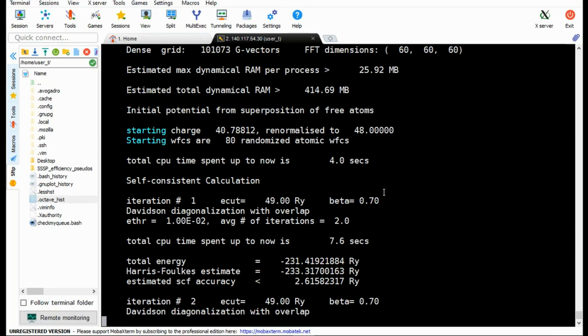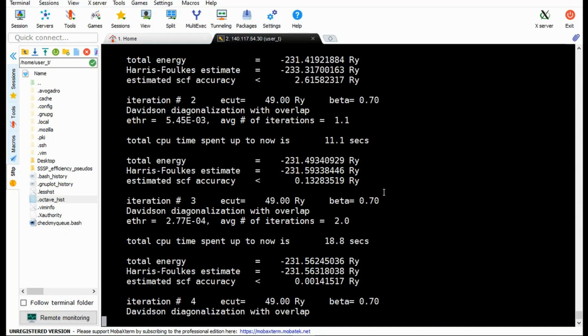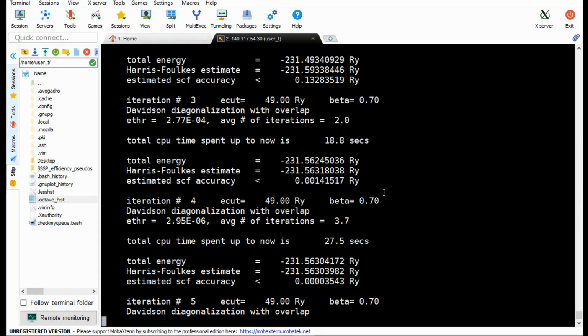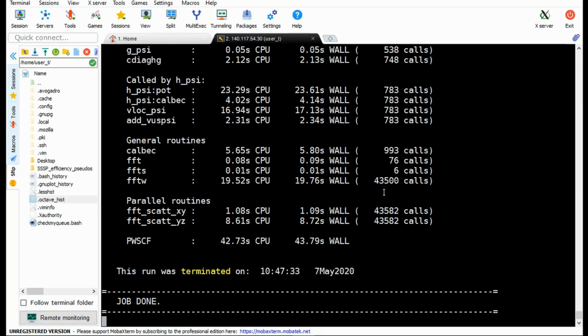So you want a density of state that is correctly obtained, at least from the computational part. If you have a metal like lithium and you get a spiky density of state, that might be a strong indication that something went wrong. But if you have a band gap for a system that is a metal, then something messed up in your calculation, and you need to find the mistake.